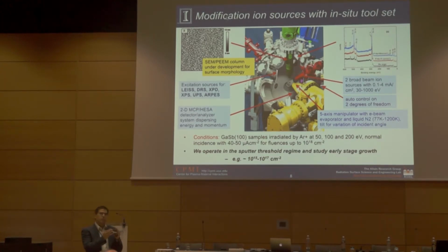Part of being able to decipher how these mechanisms evolve under radiation of ions necessitates our ability to have complementary techniques watching the surface at the same time. So what I mean by that, for example, is low energy ion scattering spectroscopy can probe the first monolayer, and we try to use techniques that in fact complement that spatial resolution. So for example, we also take advantage of using UV photons in some cases, and also look at recoils, for example, to look at the surface.